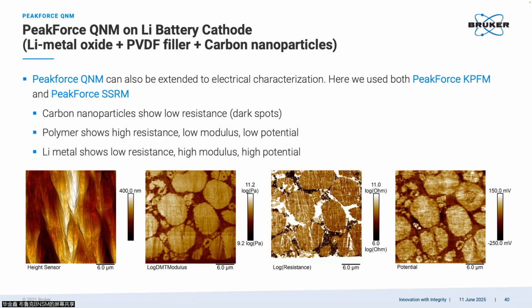Then we did some other techniques to study the conductivity. So we use the conductive AFM to study the resistance of the samples. And we found that in this soft part, some of them show high resistance and some of them show low resistance. Inside our structures, we know clearly only the carbon nanoparticles are conductive. So we would clearly know in these soft parts, those are our polymer phases. And here the carbon nanoparticles are fixed. And for other high resistance regions, it is pure polymers. And then those giant islands, we know, should be our lithium oxide.